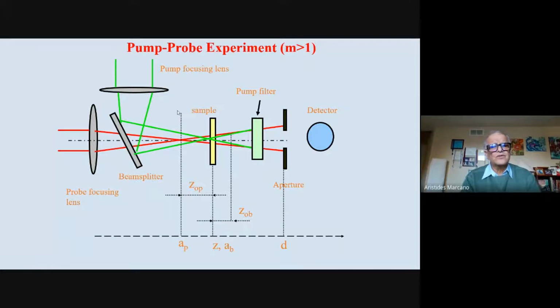And then we are using the probe. We can actually focus the probe beam, a probe beam in red, maybe a HeNe laser, for example, or any other laser of different wavelengths. And we are just sending that toward the sample, and that probe will just test the thermal lensing. So we're going to observe the probe beam only, and we're going to just block the pump. We block the pump, so we just use the pump to create the thermal lens and use the probe to test that thermal lens.